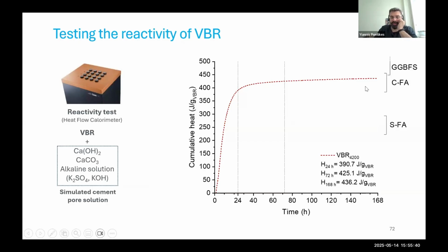And here is the R3 test that will actually tell you if you are doing good. If you are on the 400 plus joule per gram, you're probably doing quite okay. Here is the area of GGBFS. Here is the C fly ash and S-type fly ash. And here's the performance of the different materials we're making. The R3 test is also now standardized, so you can trust it. It will be a good first indication.